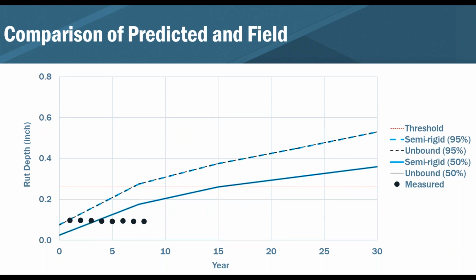So here's what the rut depth looks like, and the good thing is, since rutting is primarily in the asphalt layers, the rutting models used in both the semi-rigid case as well as the unbound case were the same, and so you would expect them to predict the same amount of rutting, and sure enough, it did. So again, I don't think there are any major concerns here on the amount of rutting between the 2 different models, but again, you can see that the rutting itself is pretty low, and not quite tracking with where it is on the predicted values.